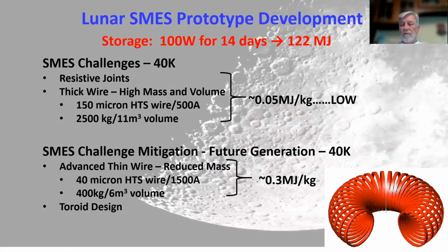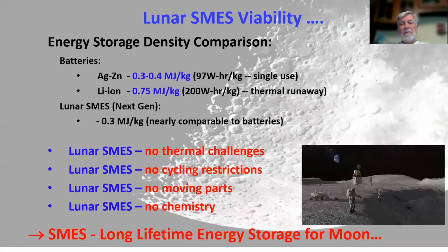So would this be viable for the moon? Well, let's look at the viability in terms of energy storage density, and compare to batteries. Silver zinc is about 0.3 to 0.4 megajoules per kilogram, and it's a single-use battery, not easily rechargeable. Lithium ion batteries have a much higher density, by a factor of 2 or so, 0.75 megajoules per kilogram. However, they have thermal runaway and they have to be heated. They cannot survive the low temperature environments at nighttime on the moon.